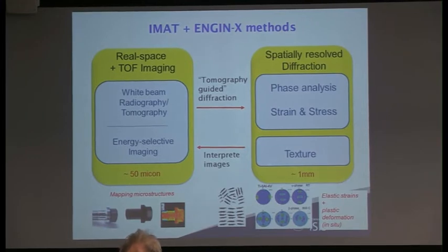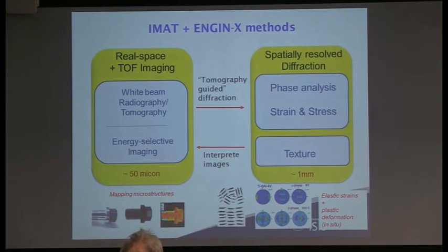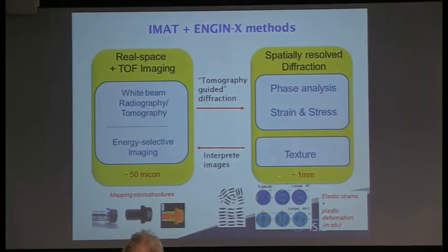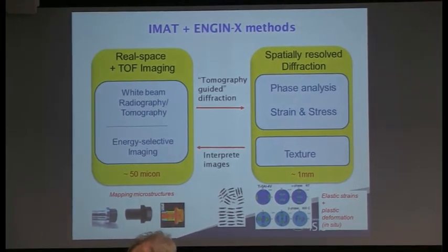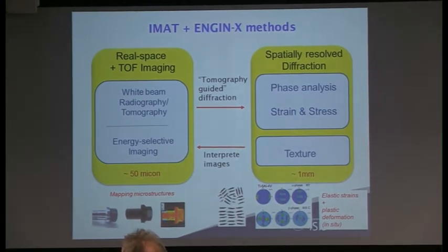And then we will have the diffraction applications, or the diffraction options, for quantitative phase analysis, strain stress analysis, and texture analysis. And we want to do this also spatially resolved, on a level of 1-2 millimeters for the diffraction analysis, compared to the 50 micron that we want to achieve on the imaging side.